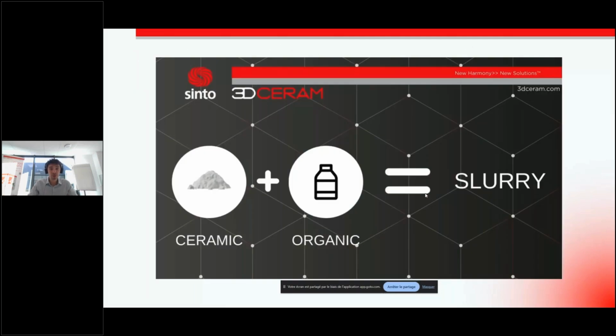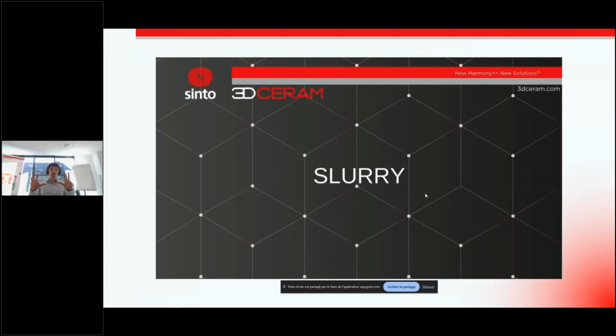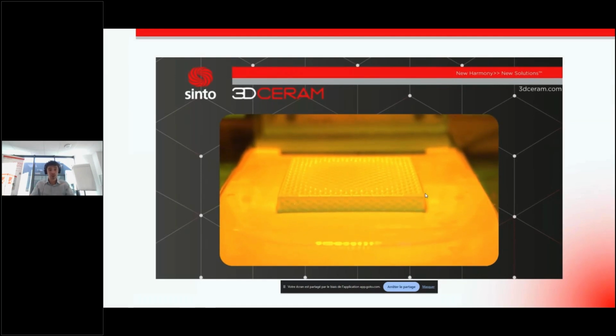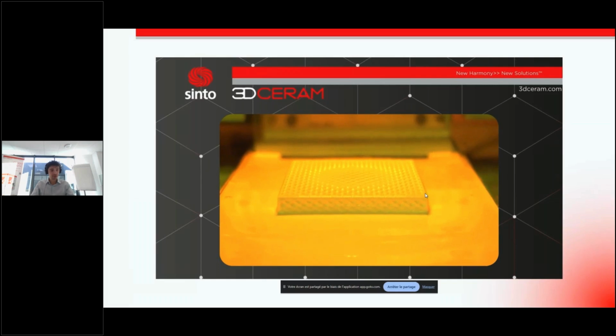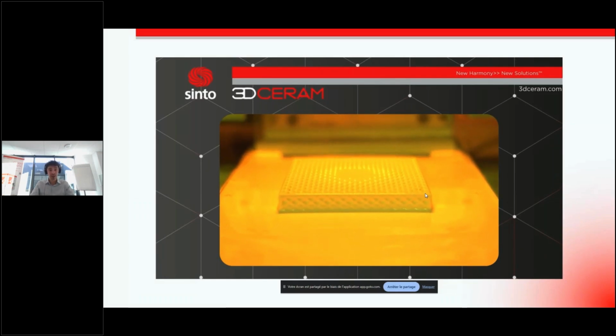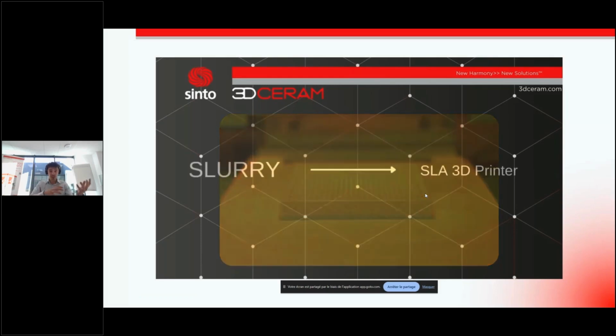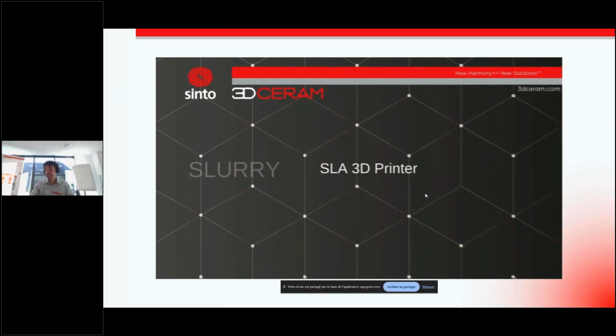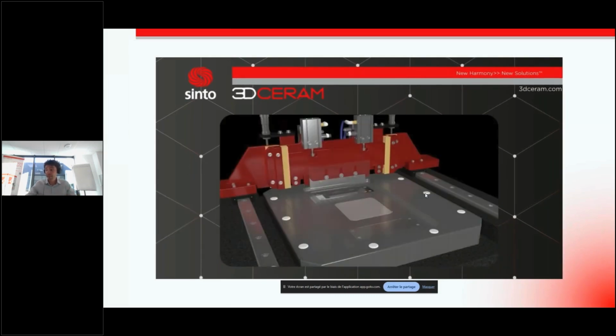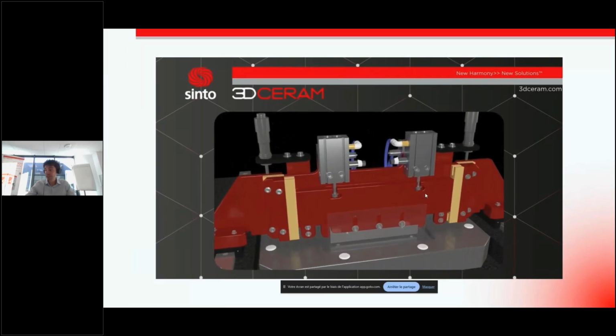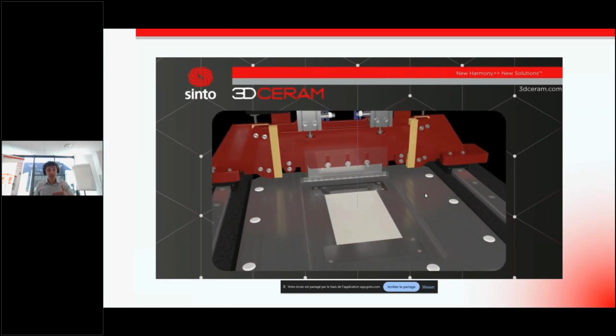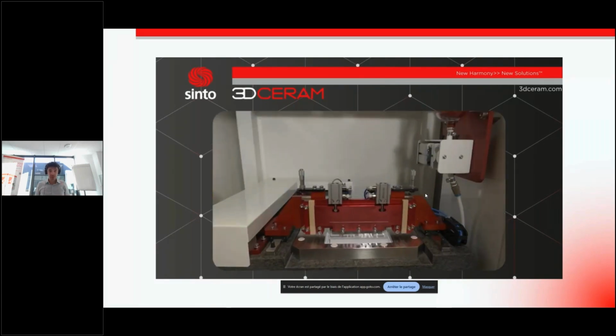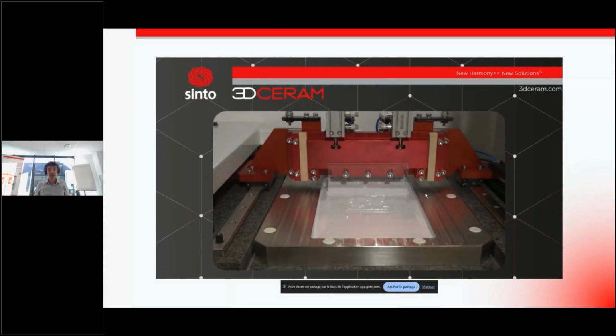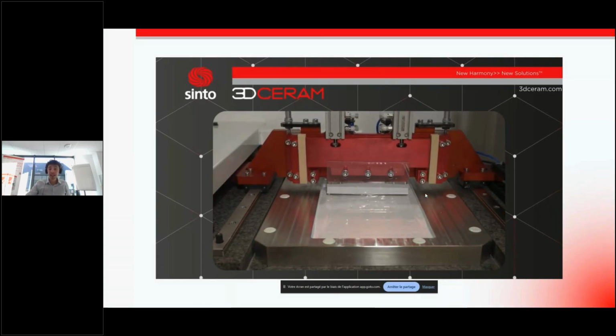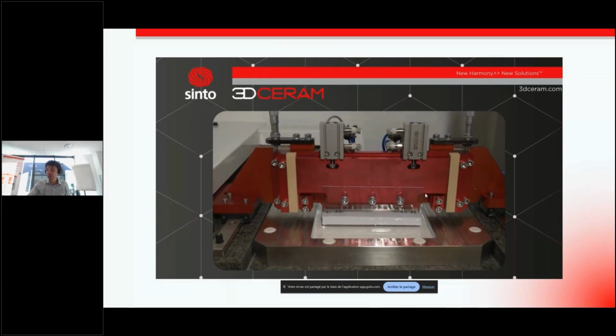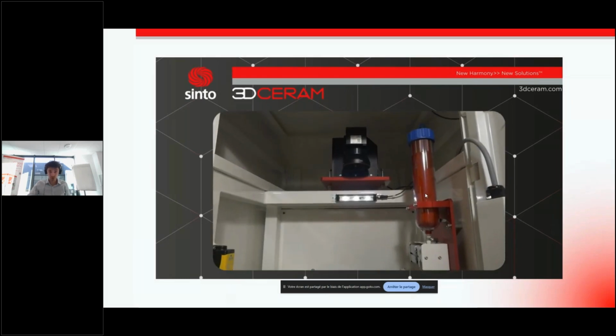Let me show you a quick video of the process. So, as I told you, the SLA, stereolithography process, uses a slurry. Slurry is a mix of ceramic powder and photosensitive organic contents. Slurry can be high viscosity or low viscosity. It really depends on the customer's need. And this slurry will be printed by the SLA printer. So the blade, the recoater system, exactly what you can see on the screen, will spread a thin layer of slurry on the printing platform, and the UV laser, at the top of the machine, will cure the area to print.